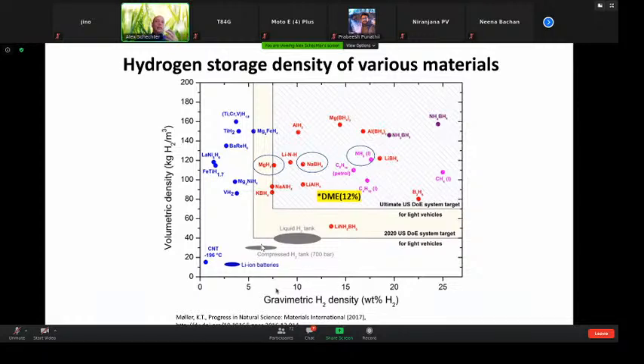So as of today, the leading technology here is compressed hydrogen, a hydrogen tank made of a Kevlar polymer reinforced with aluminum and so on, and can go up to 700 bars, which is very high pressure, and in the view of some people, even a very dangerous technology. As all of you are aware, hydrogen is not easy to handle, and it's highly explosive, despite the fact that it contains a lot of energy. So by compressing the hydrogen, by the way, we're losing about 15% of the energy content of the fuel. So that also should be taken into account.